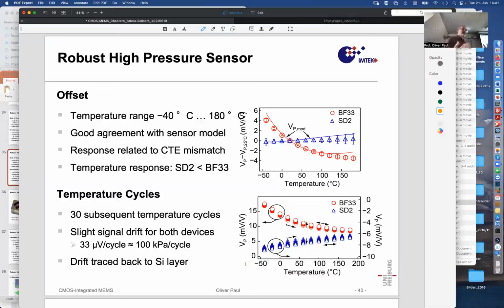problem. So when you see such drift, you always ask, what is it? Is it the bond between the glass and the silicon? Is it the glass maybe? There is it structures? And so we identified the silicon structure, not the silicon material, but the silicon layer as opposed to the glass layer, as the origin of that drift, because it happened in both glasses.